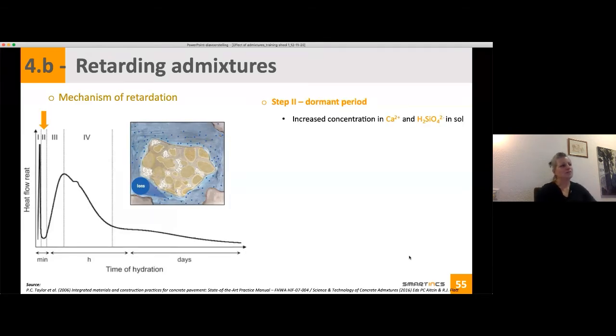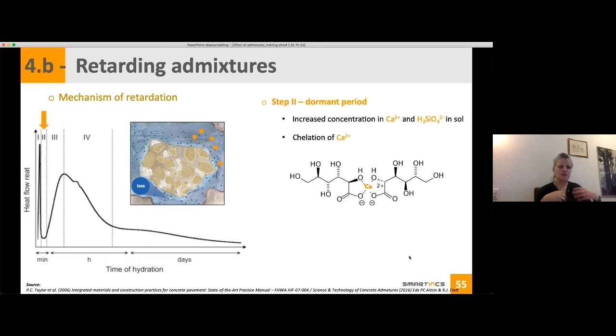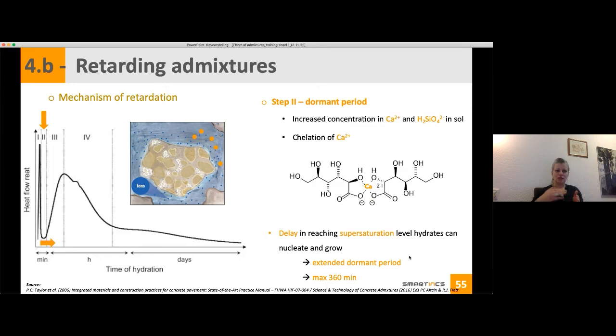How does it work? I will go back to the slide of cement hydration. Here we've seen retarding admixtures. They will extend the time for your mixture going from the plastic to the hardened phase. So it means it will increase your dormant period. In the dormant period, what do you have? You have an increase in concentration of your calcium and your silicate ions. Here it's a gluconate, so when you have gluconate in your solution, it will chelate, so it will trap your calcium, which means that in solution you will have less calcium available to reach your supersaturation. So you will have a delay to nucleate and grow your hydrates. So you will have an extended dormant period, and that should be no more than 360 minutes compared to a normal hydration.